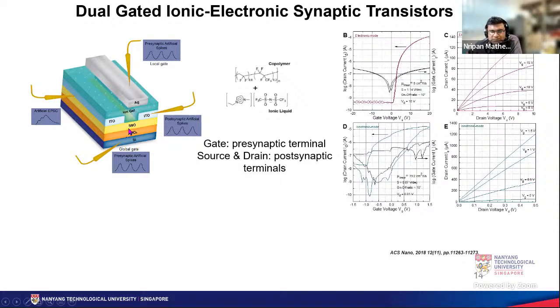In a thin film transistor structure, normally you would have a semiconductor. In this case, we are using indium tungsten oxide, which has been sputtered on top of a dielectric, and the silicon over here is highly doped, so acts as a gate. The ITO electrodes over here act as the source and drain of a transistor.